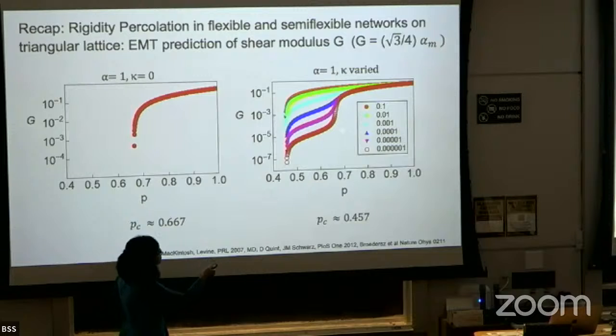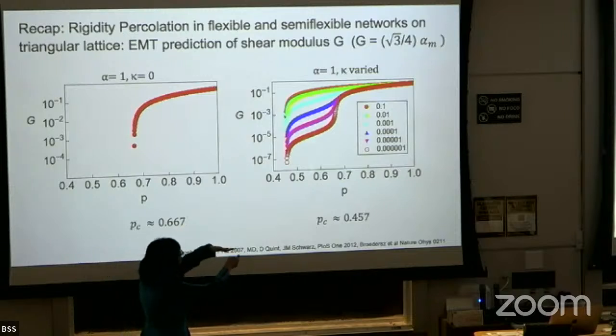So when the bending rigidity is very, very small, you can see that there is this kind of inflection here, right? And so basically, if bending was 0, it would have gone through a phase transition. So it starts falling, but then it realizes that there are still additional constraints, right? Bending is actually not 0. So then it doesn't really fully go through. And then you see this rigidity transition here.